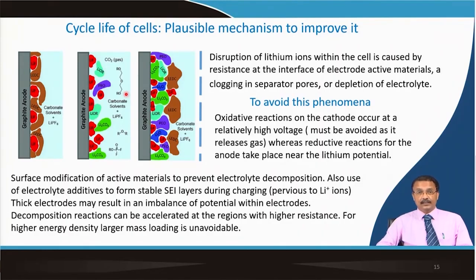Cycle life of cells is related to SEI formation, disruption of lithium ions within the cell, that is usually caused by the resistance at the interface of the electrode active materials and clogging of the separator pore or depletion of the electrolytes. So, if you want to get rid of this problem: oxidative decomposition on the cathode occurs at relatively high voltage. You remember, if I go beyond a certain voltage, then oxygen evolves from your positive electrode material, and that causes the electrolyte oxidation. And reductive decomposition also takes place at the anode near the lithium potential, when you are very close to zero. So, surface modification of the active material is one way to prevent this electrolyte decomposition, and